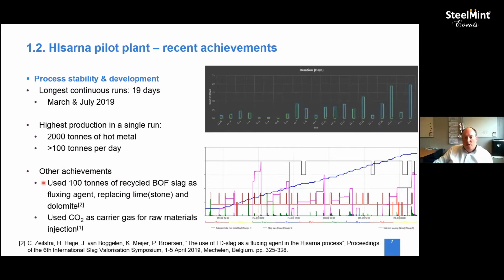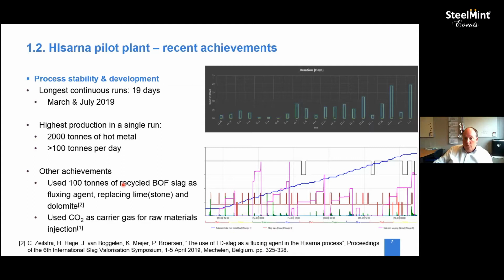The other thing we have achieved is that we managed to recycle 100 tons of BOF or LD slag as a fluxing agent to replace the limestone and dolomite we're using. That worked really well, actually. So for us, a key development that would have to happen relatively soon, in my opinion, is that we have a process here on the site that could granulate LD slag efficiently in the right particle size, because that would save us buying limestone and dolomite as a fluxing agent. And it also is a much higher value application of LD slag than the route where it goes now, where on our site it largely goes for road stone and hard standing.